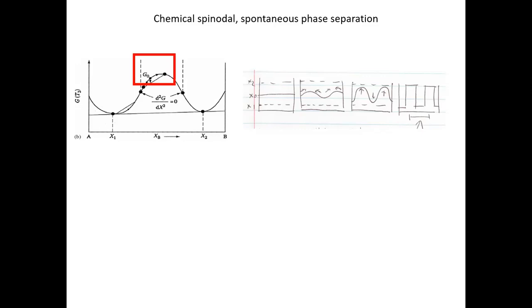So this is different from, like, eutectic transformation and things like that. You just deal with the same solid structure and only deal with diffusion of the solutes, or motion of the solutes, I'd say, rearrangement of the solutes into different regions. But the thing that you see here is that, from the diffusion point of view, if we consider this kinetics to be diffusive, this is going to be our starting point, right? And we did this many times when we discussed diffusion. You're going to start with a fluctuation like that, and diffusion will do what? The diffusion will smooth out the fluctuation and take you from this case all the way to this homogeneous case, right?